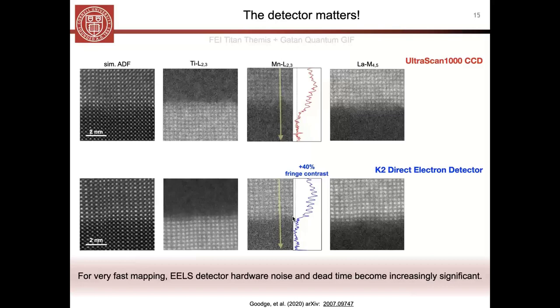And so, again, as I said, once you enter this inherently signal-limited regime, the efficiency and the low noise of your detector really start to play a big role. And that's what we can see in these maps here. The other main advantage of the direct electron detector that you actually can't see from these maps until I give you access to some of the metadata statistics is the amount of time that they take to acquire. And so here what you can do is count up the number of pixels and the exposure time per pixel, and then you can measure how long it takes from the start to the end of the map.